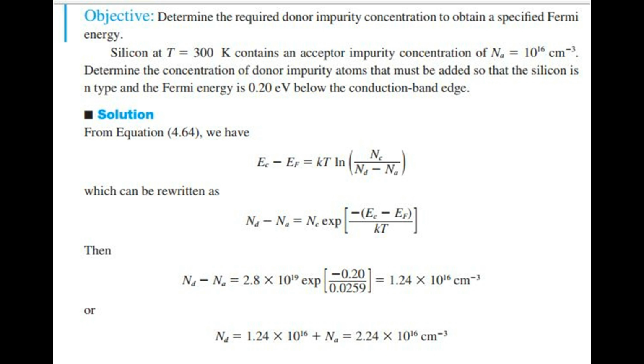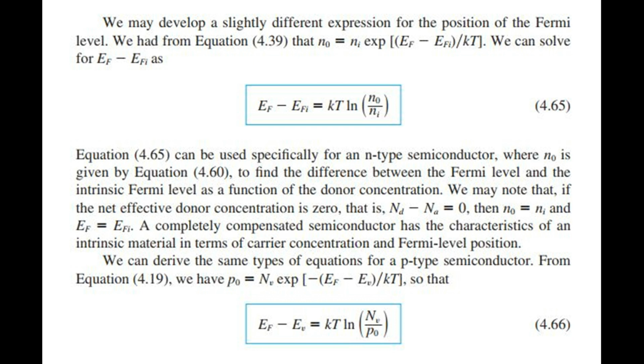Solution. From equation 4.64, we have, which can be rewritten as, then, or. Comment. A compensated semiconductor can be fabricated to provide a specific Fermi energy level. We may develop a slightly different expression for the position of the Fermi level. We had from equation 4.39 that n0 equals ni exponential of (EF minus EFi) divided by kT. We can solve for EF minus EFi as, equation 4.65, which can be used specifically for an n-type semiconductor, where n0 is given by equation 4.60, to find the difference between the Fermi level and the intrinsic Fermi level as a function of the donor concentration.